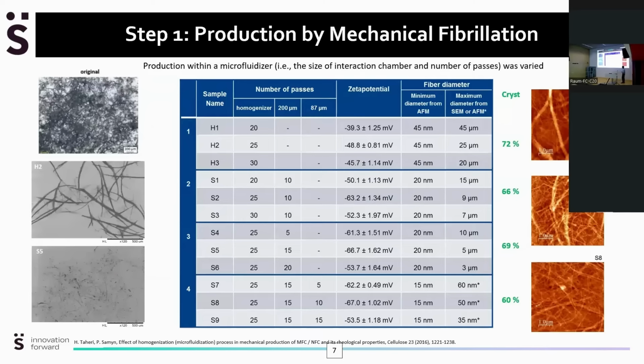So here you see some lab results where we have applied different numbers of passes into a homogenizer, with a 200 micrometer chamber or an 87 micrometer chamber. And of course, with an increasing number of passes, we see increasing fibrillation and a decrease in the size of the nanocellulose fibrils. One parameter to control the suspension stability is the zeta potential that we have measured.